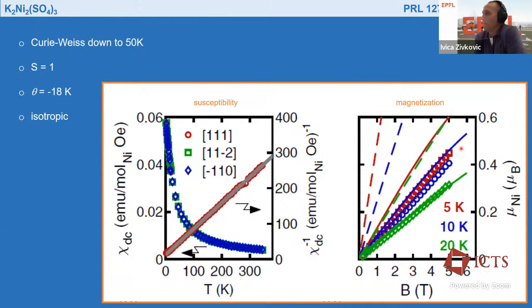Okay, so we are now focusing on the results of our investigation on the langbeinite which contains nickel. And you can see here the reference. From the magnetization point of view, you can see that at high temperature it follows nicely Curie-Weiss behavior, with the slope corresponding to spin 1, which is in agreement with nickel. And then it gives you the average interaction between the moments of antiferromagnetic type, and the size is roughly 18 Kelvin. As far as we could see, the behavior is isotropic above 2 Kelvin.